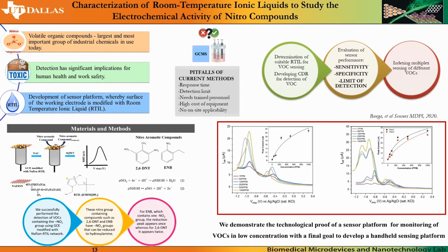We worked on this as a proof of concept because environmental air sampling is much easier as compared to breath analyzer development. So we wanted to show that the developed sensing platform works. Herein we used a glassy carbon electrode, which was modified with Nafion and RTIL, which was then used for detection of nitroaromatic compounds, and square wave voltammetry was used as the electrochemical transduction mechanism. We were significantly able to differentiate between 2,4-DNT and ethyl nitrobenzene because of the difference in the number of nitro groups, which can be seen from the reduction peaks. Here, two reduction peaks were seen for the NO2 groups, whereas in the case of ethyl nitrobenzene, only one reduction peak was seen. So this was a proof of concept demonstration of using RTIL for VOC sensing.